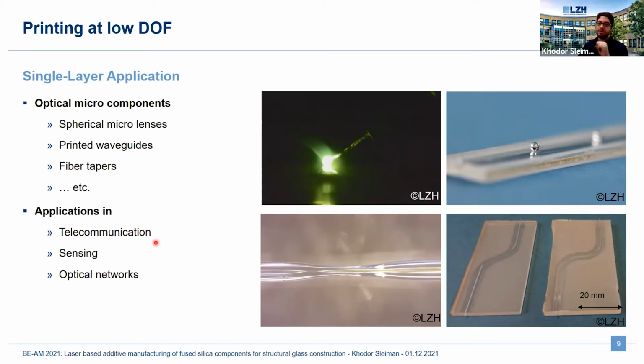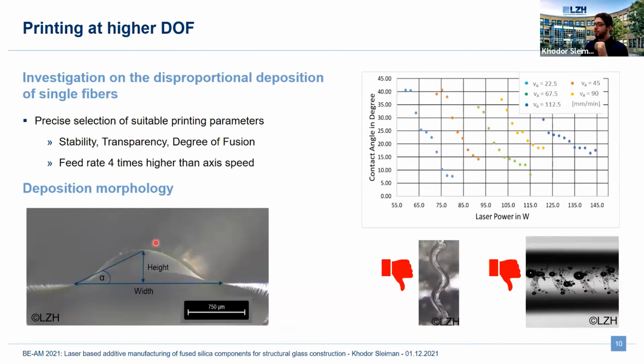So, but I want to go more toward the printing with a higher degree of fusion, where we use a disproportional deposition of the glass filament. So we use a higher feed rate than the axis speed to deposit the fibers. We conducted experiments to select suitable print parameters for stability, transparency, and degree of fusion or contact angle. Because if you do not choose your parameters right, it might look like this, a shaky form, or it will have a lot of bubbles in there.